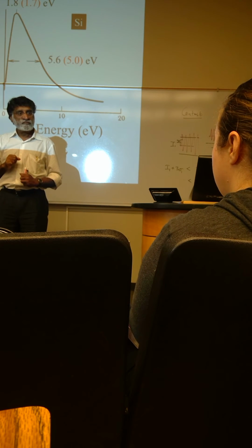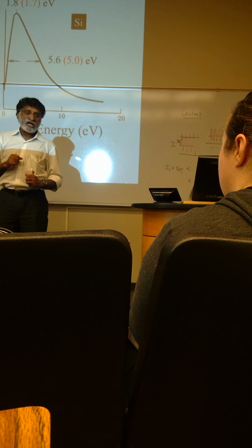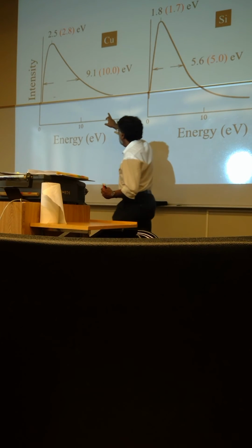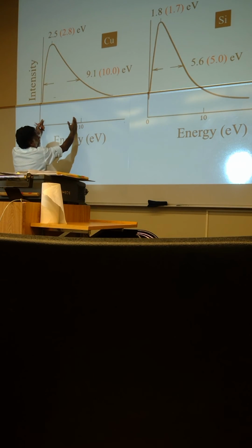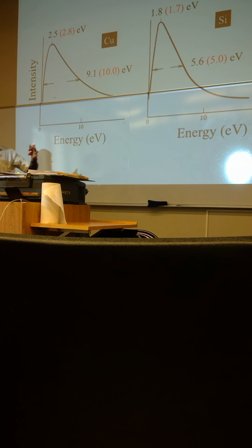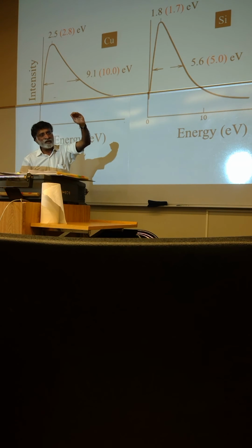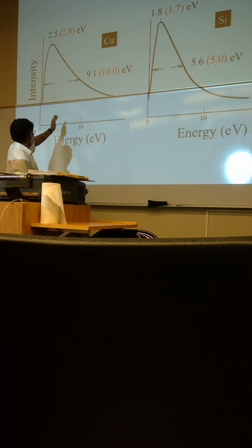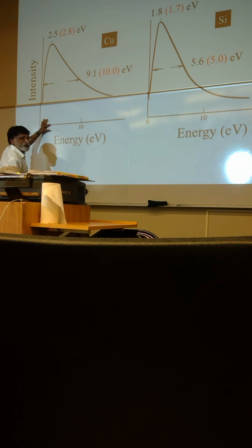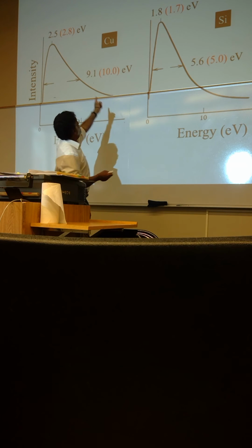What does the width of the peak tell us again? It just says that it's a statistical process, so typically what is happening is that it has this range of energies, and it will also tell you the sort of depth over which the secondary electrons are coming as well. Okay. But the peak tells you that they're mainly coming to the surface. There may be a smaller one that comes from a little bit further depth of the sample. And it changes with the atomic number.